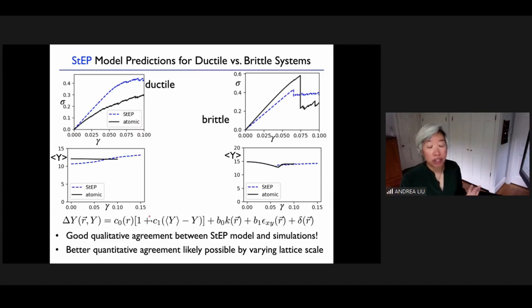Okay. And what we find is that for the brittle case, there is actually a term proportional to XY strain, and now this coefficient becomes important. Before it was negligible, now it's important. So when we do that, we do manage to capture ductile versus brittle behavior. In the ductile system, the stress strain curve rises and flattens out, and we do not see any shear banding. For the brittle system, we see a shear band, and we see this drop in the stress strain relation. Not as big as in the simulation, but we do see it.